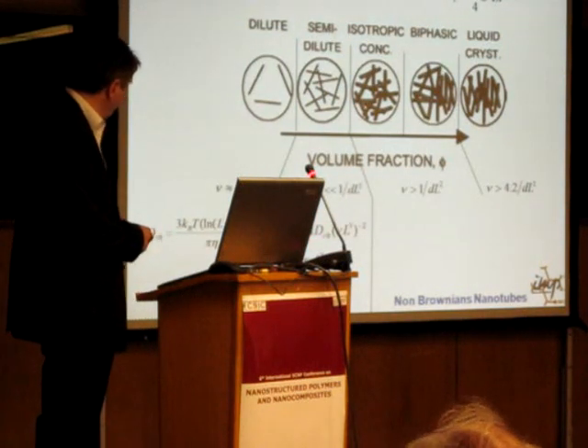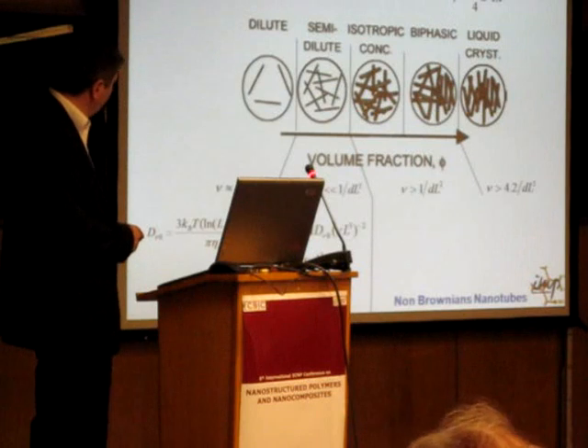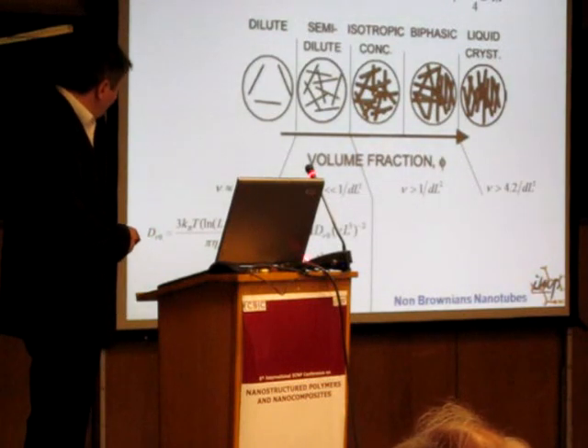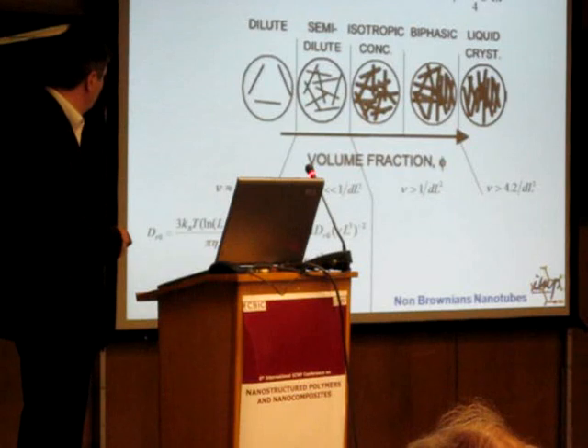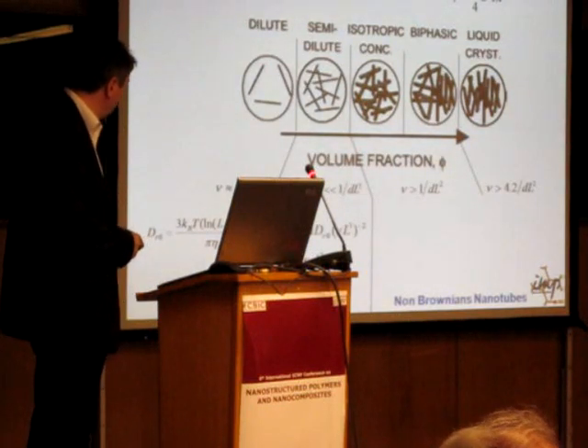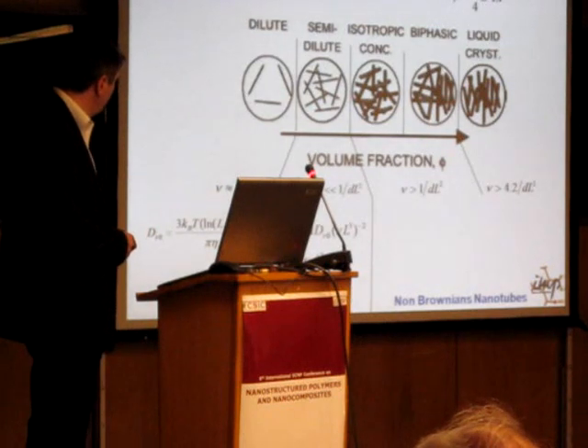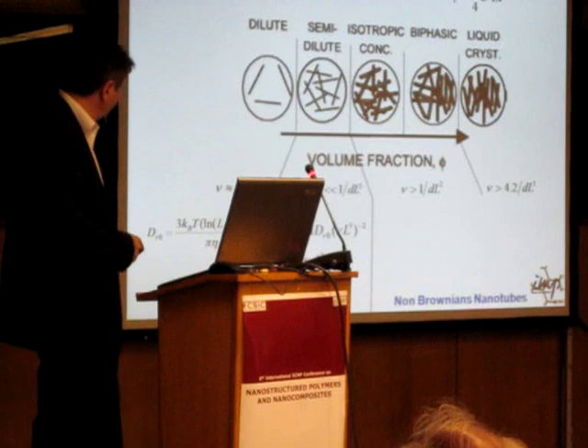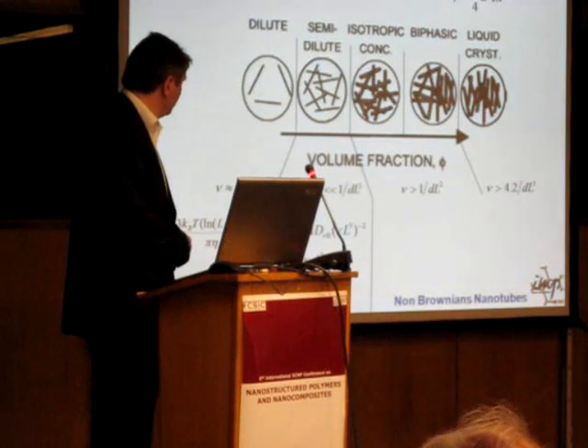And from this coefficient of diffusion, we can predict the variation of the zero shear viscosity. The zero shear viscosity proportional to the cube of the concentration, and the relaxation time of the Brownian motion of nanotubes, which is proportional to the square of the concentration.